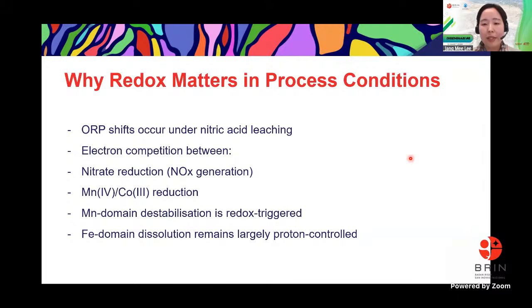So why does redox matter in process conditions? Under nitric acid conditions, redox reactions are unavoidable. Nitrate reduction generates nitrogen oxide species like nitrogen dioxide or nitrogen monoxide as gas, and can generate reactive nitrogen species, particularly at elevated temperatures, and this also shifts the ORP of the system. This introduces an electron competition reaction. The electrons can be consumed by nitrate reduction, or by the reduction of manganese and cobalt to their soluble 2+ oxidation state.